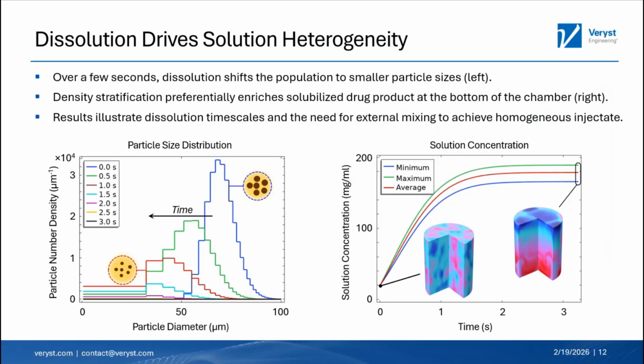So going a little deeper in these particular simulations, we can actually quantify the dissolution and mixing by plotting the particle size distribution and solution concentration versus time. So the particle size distributions are shown, snapshots of that are shown in the left plot. For a given initial particle size distribution, this would need to be measured for a particular drug product or powder. The dissolution shifts the population to smaller particle sizes over a few seconds. Particle sedimentation under gravity leads to vertical particle density and concentration gradients.